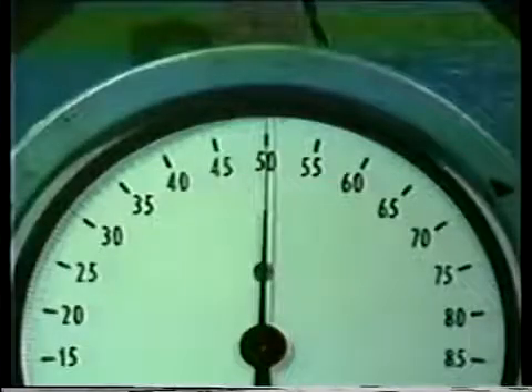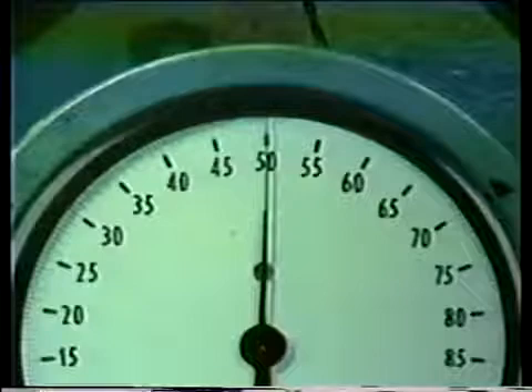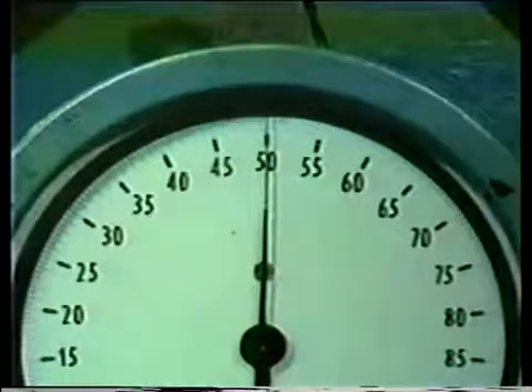By now, the pressure should be starting to compress the manway gaskets. Leave the manway nuts hand tight. Let the boiler do some work for you. Inside boiler pressure will compress the gasket more evenly and make a tighter seal. In order for handhold gaskets to seal properly, the boiler pressure must be higher than 20 pounds per square inch. So, take the boiler pressure up to about 50 pounds per square inch, or 345 kilopascals. At this pressure, the boiler will compress the handhold cover gaskets the way it compressed the manway gaskets. Check for leakage. If necessary, tap the handhold cover with a hammer to reposition it and stop the leakage. When all leakage is stopped, tighten the cover nuts. Now, the boiler is ready to be fully pressurized.